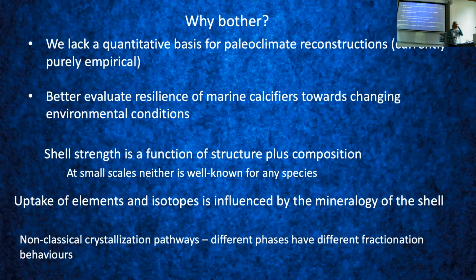And of course, uptake of elements and isotopes and fractionation of these things is influenced by the mineralogy as such, and therefore eventually we have to understand how that actually works. The basis of this, which I get to later, is that most of these marine calcifiers, as we know now, crystallize their shells through a non-classical crystallization pathway. That involves different phases. They transition through several metastable phases until they actually reach the stable calcite phase.